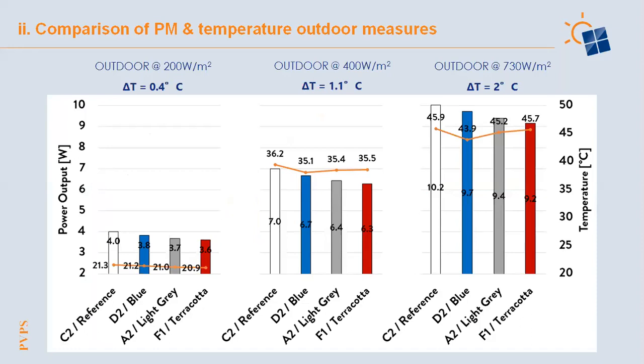So these are the same results, but in more detail. From the evaluation of 3 different moments during this clear day, we have the detail of the different temperatures that we monitored among modules. From this section, it arises that the main influencing parameter on the electrothermal behavior is the color type, even if the operating temperature seems not to affect the power output significantly, also because in this case, for these prototypes, we applied a low percentage of color, even if this color can be seen on the modules. So the cells cannot be seen from a far distance.